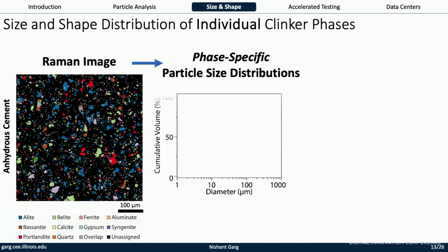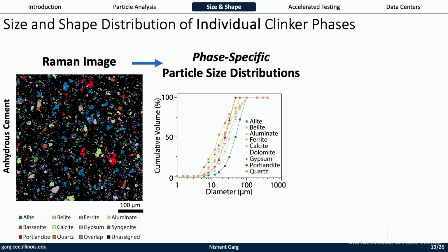And by this, what we can do is, for your cement, instead of having one particle size distribution for a powder, you can have phase-specific PSDs, right? Because we know that powder is made of 10 different powders. So you can get a PSD for quartz and a PSD for alite.